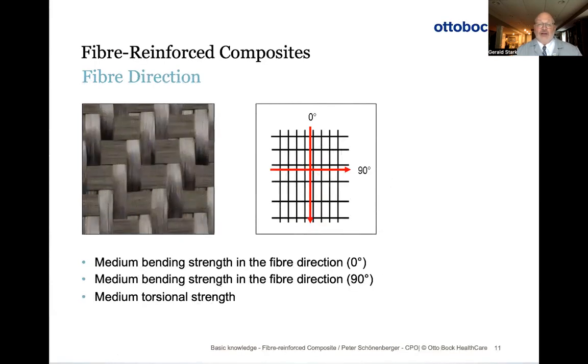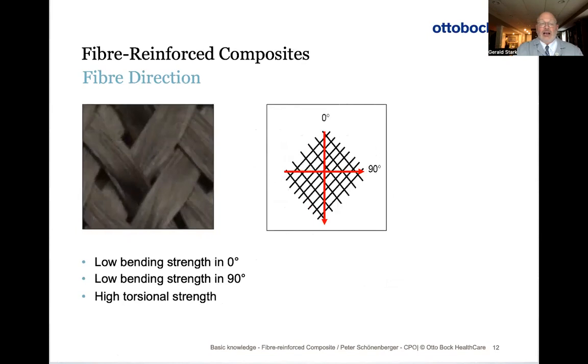If we have a 0-90, we have a medium bending strength, medium torsional strength. So we're increasing that torsional strength a little bit more in the opposite direction. And then the fiber direction, this is what I was getting at with the 45-45. Know that it's actually, the resistance is in the direction of 0 and 90. So it's actually at 90 degrees from where we think it is typically. Many people think that the direction is bidirectional by looking at the weave, but it's actually across the matrix in a sense.